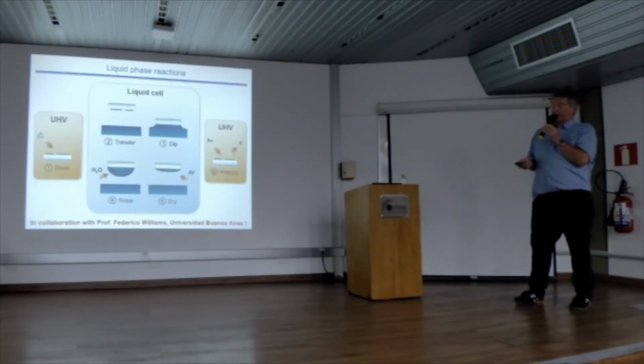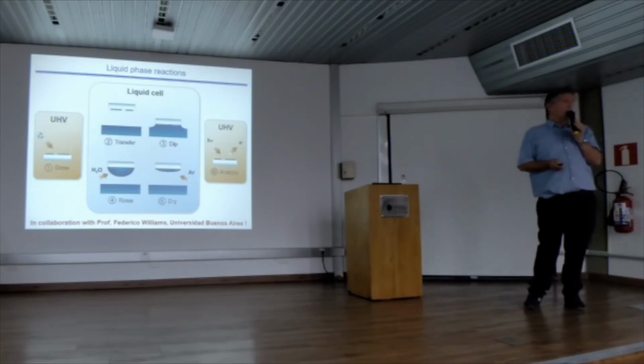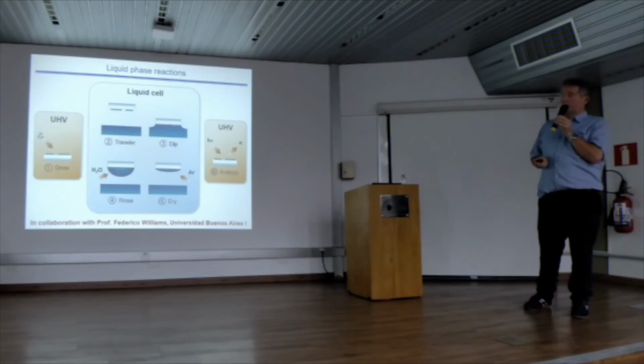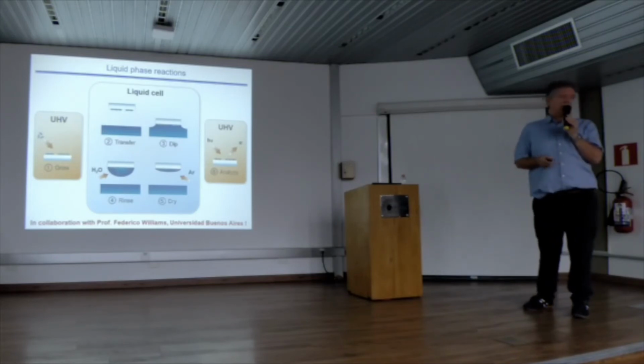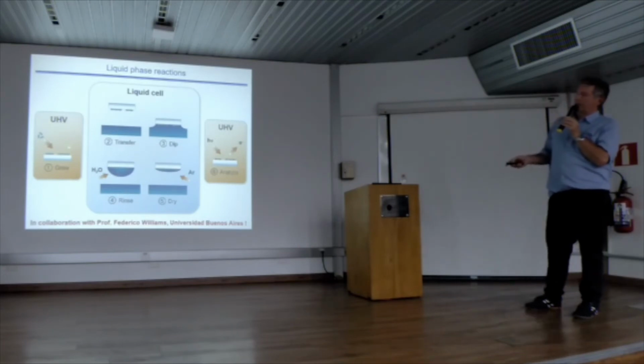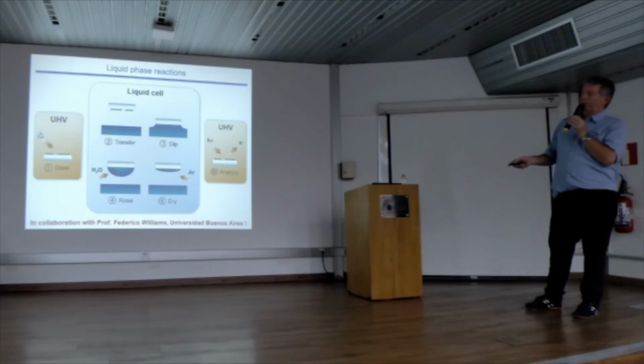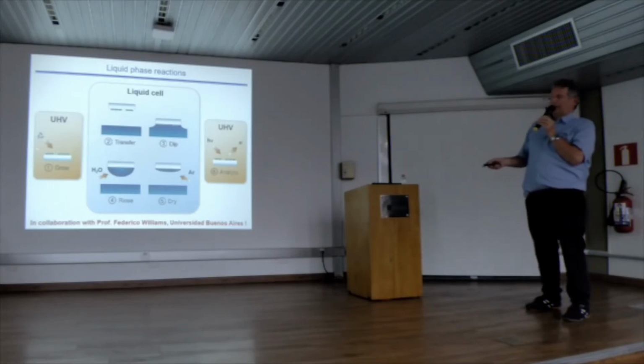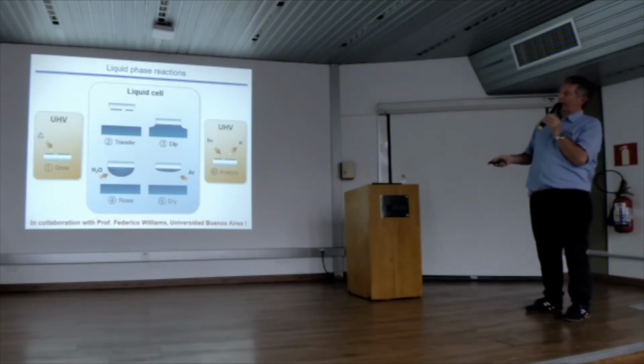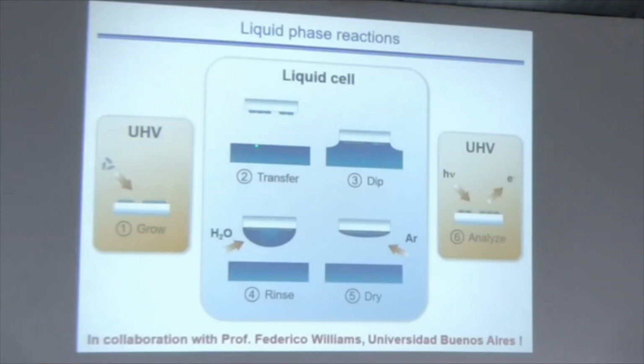Federico Williams, whom some of you know, is from the university in Buenos Aires, and he measures every once in a while here at the synchrotron. He developed a setup where you first prepare your sample in UHV, using the standard methods with well-defined ordered layers, and then he transfers the sample into the so-called liquid cell, rotates it by 180 degrees, so it's upside down, lowers the sample into an electrolyte containing, for instance, metal ions, then pulls it out, rinses it with water, blows it dry with argon, moves it back to the UHV system and analyzes.